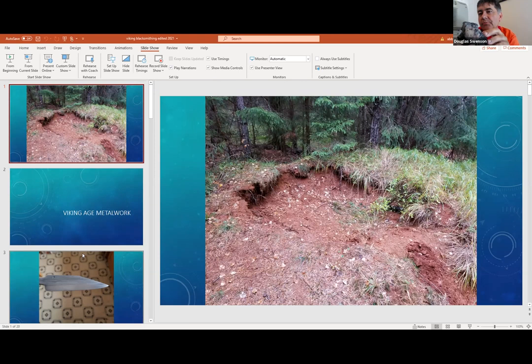You work with this, hammering, compressing, reheating, compressing, maybe for an hour and a half, and finally you end up with a small little bar of pretty much pure iron, such as this, that has been drawn out, folded over, and welded several times. This is the raw material that you can finally start forging and blacksmithing with to forge your blades and tools and that sort of thing. So again, a tremendous amount of effort invested in making iron during this period, making it extremely expensive and really quite rare.